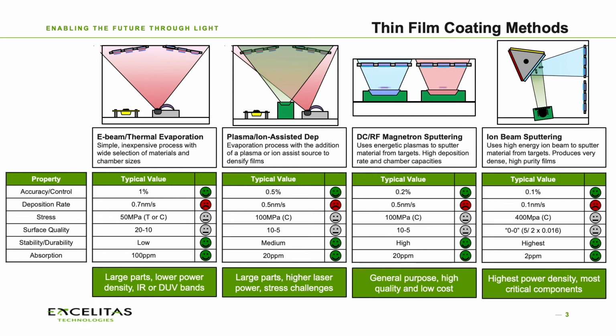It's a good general purpose process. Where it really shines, though, is when we have significant out of band specs. If there's a lot of infrared requirements, or if we're getting into UV requirements, sometimes the material choices will be such that it'll be desirable to use an evaporation process, because it is the most flexible in terms of the palette of materials that we can choose from. It has significant trade-offs in terms of the accuracy and the control, the surface quality that's typically achieved. Can be challenging. The durability can be challenging. And we certainly won't get the low levels of absorption that we'll get with the more energetic processes, but it comes with other trade-offs that sometimes can be a benefit.